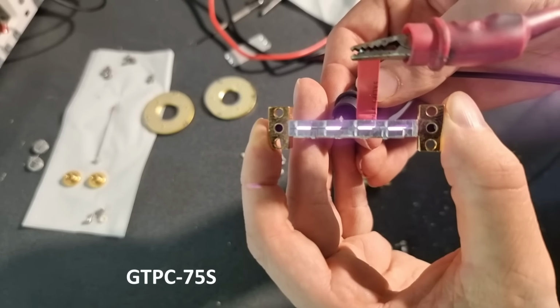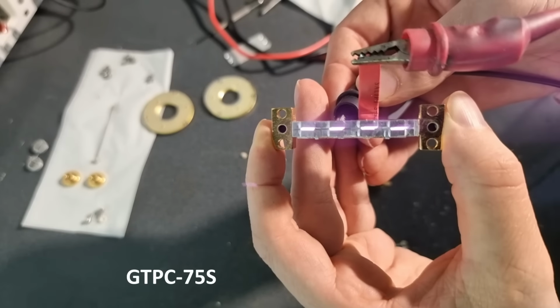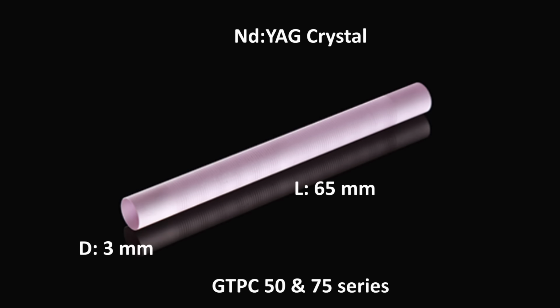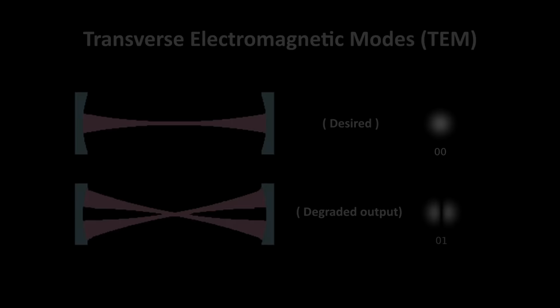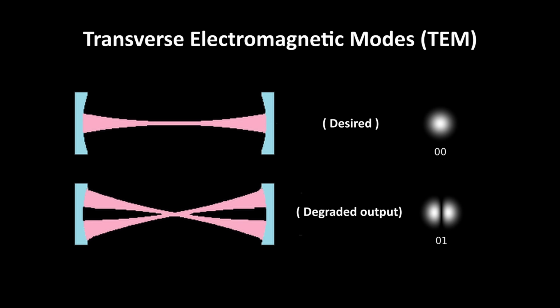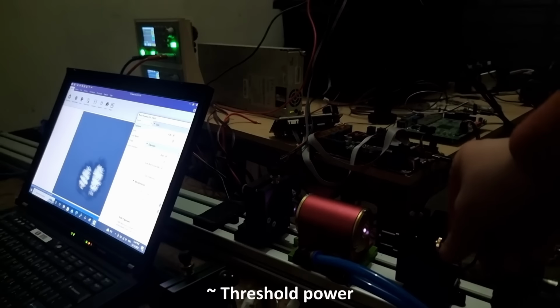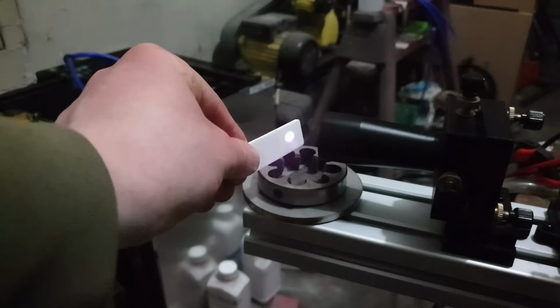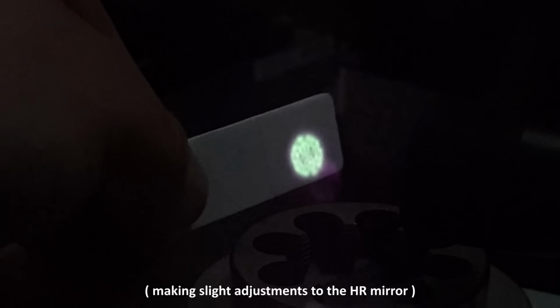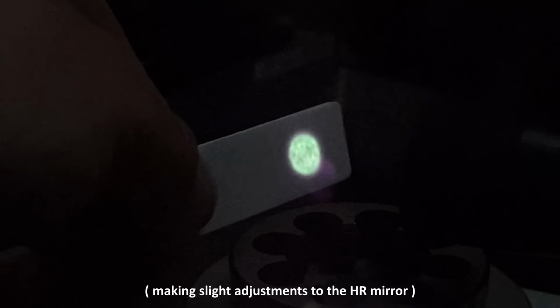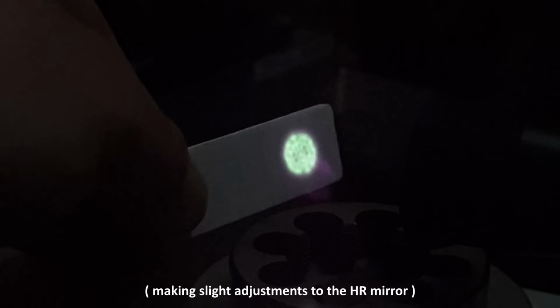Since this is a side pump laser, the gain medium is much shorter than that of a fibre laser, and to achieve the same order of power requires a much larger cross section. This unfortunately increases the possibility of resonant modes on axes other than the optical axis, meaning that the output beam is composed of a series of rays rather than a single fundamental mode. This results in a multimodal beam, lessening its ability to form a tight focus, leaving the spot size compromised, which of course lowers the power density, print speed, and increases the feature size.